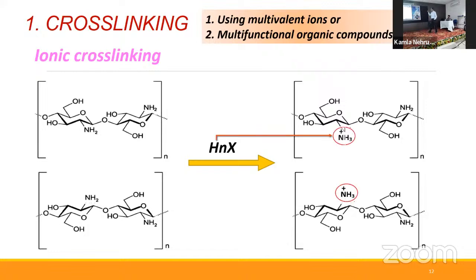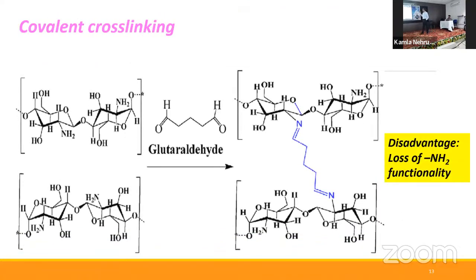So if we simply take chitosan and carry out a reaction with simple multivalent acids, like say H2SO4 or phosphoric acid, you will find that the NH2 group gets converted into a protonated amine group, and then the anionic part of this can act as a bridge between the two. So it is an ionic cross-linking between the two by using a multivalent ion or multivalent acid.